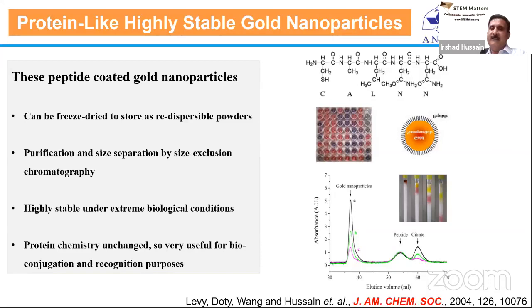And for that purpose, we screened different peptides that have a cysteine residue at one end so that they can covalently link with gold nanoparticles. And we found, working in collaboration with Professor Levy at the University of Liverpool, that this CALNN peptide gives extra stability to these nanoparticles, and they become so stable that they can even withstand sodium chloride concentration of up to 3-4 molar, which is really huge. Otherwise, they cannot even withstand a few micromoles of these sodium electrolyte concentration.